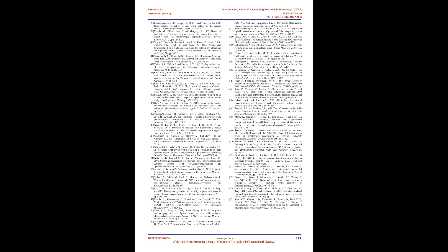The effect of binding amino acids on interfacial energies of growing calcite crystals has been investigated by atomic force microscopy, molecular modeling studies, X-ray photoelectron spectroscopy and surface X-ray diffraction studies 175. The unprecedented finding of an increase in hardness with the incorporation of amino acid in calcite crystal was observed 176.